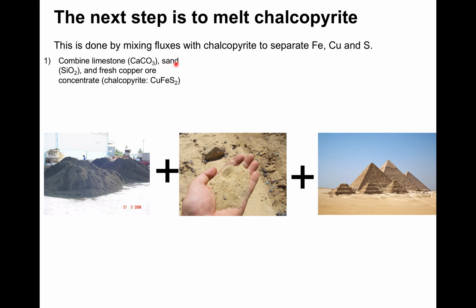We're going to do that by mixing the chalcopyrite with what we call fluxes. We're going to start with our chalcopyrite here on the left side. We're going to mix that with limestone, which has this composition, calcium carbonate. We're going to mix it with sand, which is quartz and has a composition of silicon dioxide. And when we mix these three solids together, so chalcopyrite plus beach sand plus calcium carbonate, which is what the limestone pyramids are made of in Egypt, we're going to put this into a furnace, and I'm going to show you first an animation of the process so you can visualize what's happening, and then I'm going to walk you through the details of the chemistry.